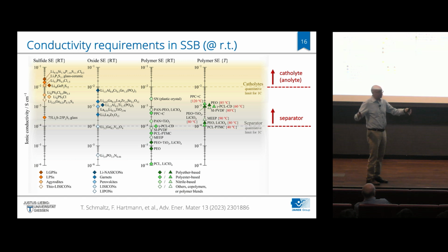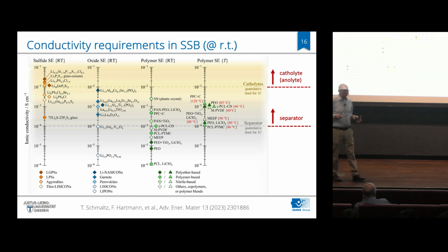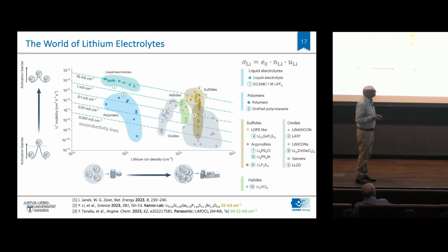Let's say typically 100 micron. And there, the constraint is you need at least 10 millisiemens per centimeter, roughly. And only really today, sulfide electrolytes achieve that reliably. Unfortunately, these are the most sensitive electrolytes. Polymers don't. True solid electrolyte polymers don't achieve that. Oxides just scratch that, but not really good enough.